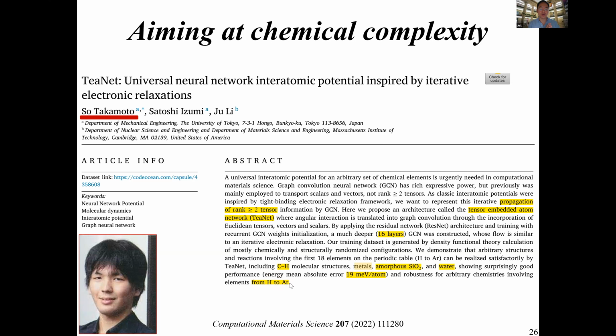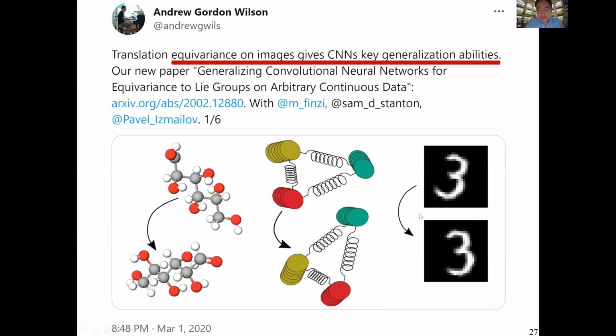Because if you bias the neural network, very often what happens is it hallucinates. In other words, if we don't tell it that argon bonding with carbon with chlorine is a very unlikely situation, that energy for this is very high, then it could actually dream up an argon bonding to 4 carbon and 1 chlorine, right? So in the training, we really just randomly throw these atoms together. And the other thing that we need to pay attention to is this issue of equivariance.